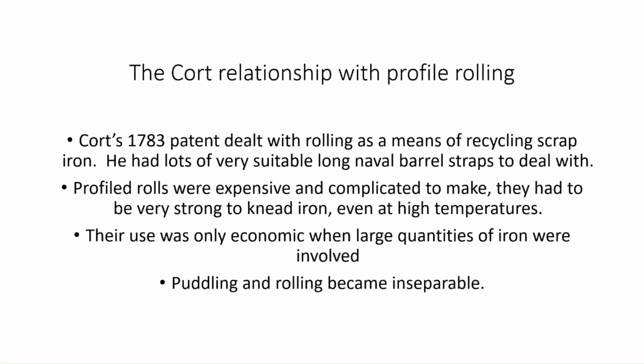Cort actually patented this process and used it because before he invented puddling, he was recycling wrought iron from the Navy, and he particularly was given a whole load of barrel hoops that were nice and long and were actually, in some ways, quite difficult to recycle. To recycle wrought iron, very simple. You heated it up, having cleaned it, and then just beat it together. And actually, if you made a decent piece of wrought iron from a whole mixture of scrap, it could be very, very good because you were getting it much more homogeneous than it started off as.